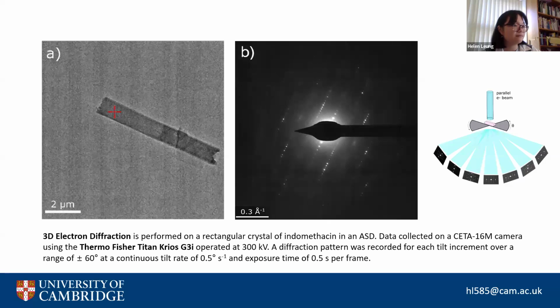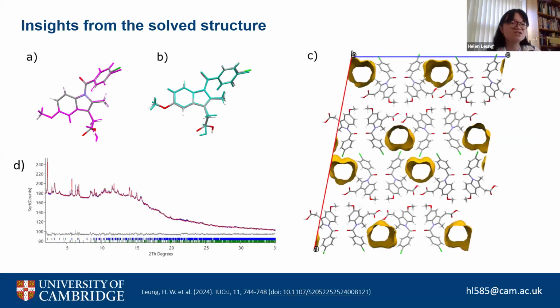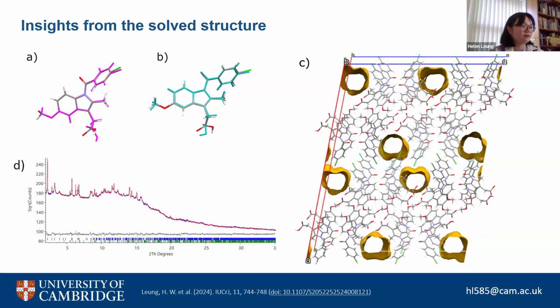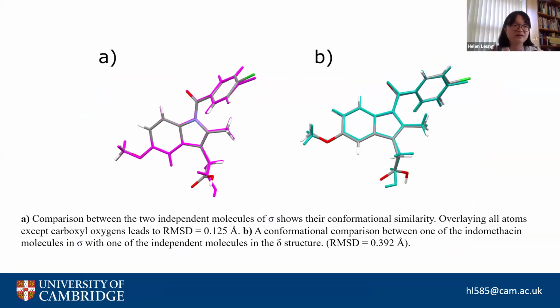And this essentially was able to give us a structure solution, which I say trivially, but it actually took a long time to do. And what's really important about this is the way that this indomethacin molecule is molecularly, in terms of its conformation, can tell us a little bit about the way that it came about. And so we call this new polymorph the sigma polymorph, and you can see that it matches up in terms of conformation quite well with itself. So we can start comparing that to itself and understanding the conformation of that molecule.